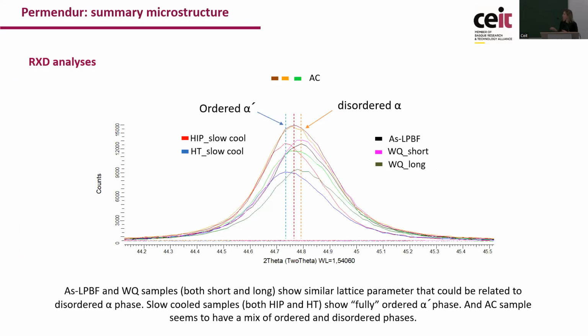So coming back to the microstructure, here we can observe the X-ray diagram, in this case a magnification of a peak, where we can see that as a function of the heat treatment that this material has, the maximum of the peak is displaced to either one side or to the other. The ones on the right side are related with disorder alpha. So in this case, we have the ones that have been fast cooled, either as SLM or after heat treatment with the fast cooling. So this will be the phase that is giving the good mechanical properties, but bad magnetic properties. On the opposite side, we have the peak of the phases that have alpha prime, so good magnetic properties and bad mechanical. And in the middle, we can observe that there is another peak, and these are related with the materials that have been intermediate cooled. So they are supposed to have a mix of those two phases.